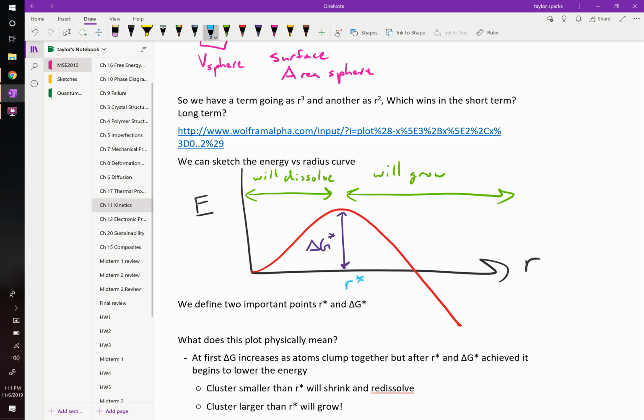It's just that we're putting a bunch of them together, and all of a sudden now that big clump of atoms, we could assign it a radius. If it's a spherical clump, we could say maybe that's a nanometer big, or that's 2 nanometers big, right? And that's the radius r that we're talking about. And there exists a specific value of r, which we're going to call r star, or the critical radius. If you're less than the critical radius, that glob of solid is going to redissolve again, because it's going to go down the energy landscape this way. But if it's on the other side of your critical radius, it's going to keep on growing. It will never redissolve again. That makes sense? Back to a liquid?